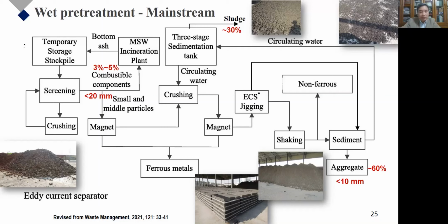The aggregate product is of poor size grading, so it is mainly used in building materials such as bricks and cement blocks. About 30% of the bottom ash will end up in the sludge, which is enriched in heavy metals and is then usually landfilled or just dumped. Furthermore, its recovery efficiency for aluminum is not good, and water consumption is high, around 0.5 ton of water for 1 ton of bottom ash considering water recycling. However, the wet process has a good separation efficiency for copper compared with the dry method, which has a higher value, so it is more profitable. As a result, it has become the main technology for bottom ash pretreatment in China.